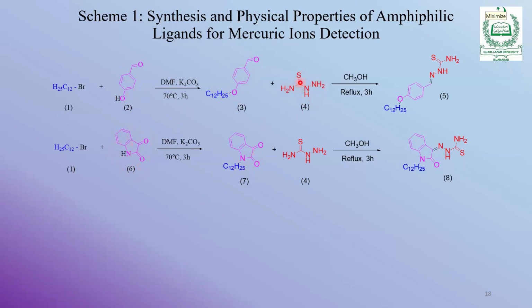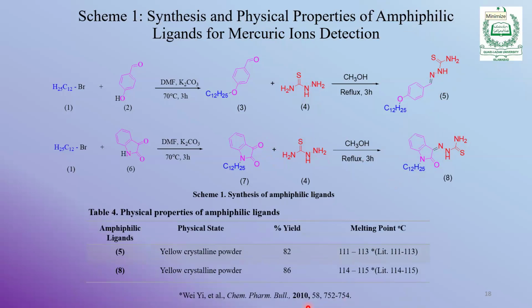Then we use this thiosemicarbazide to form the derivatives, a Schiff base derivative of this aldehyde and this isatin. So you see one of the carbonyls of the isatin forms this imine with this molecule. Why thiourea is used: thio or sulfur is used because mercury ions have a very good affinity towards sulfur. So that is why we are designing our amphiphilic ligands for the detection of mercury ions. These two amphiphilic molecules have been reported otherwise. So this was the reported one. See what we have done.